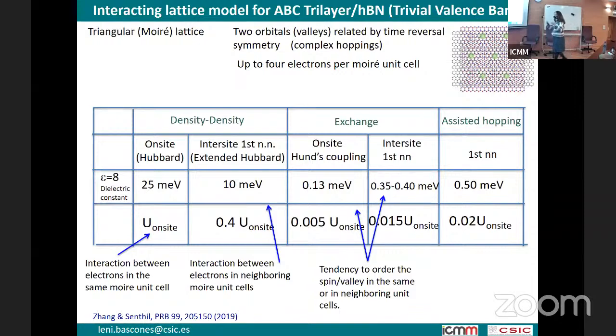So then they also studied the interactions in this system. We have different kinds of interactions. We have density-density interactions, so just charge interactions between the electrons, and the largest is between the electrons which are on the same site. This is the Hubbard interaction, the on-site one, which is of the order of 25 milli-electron volts.